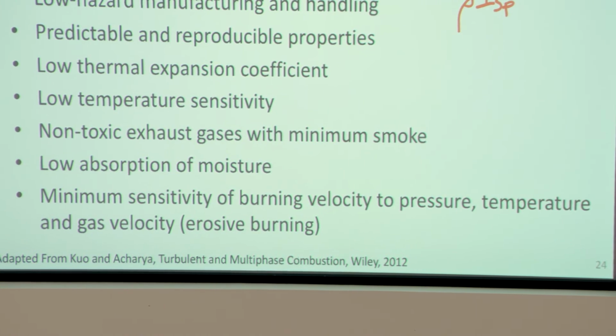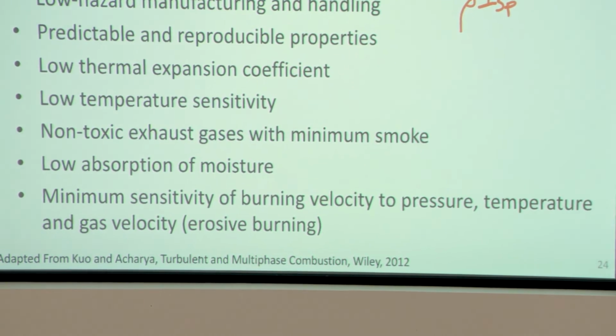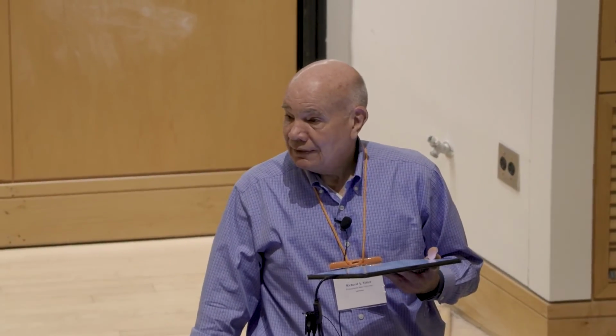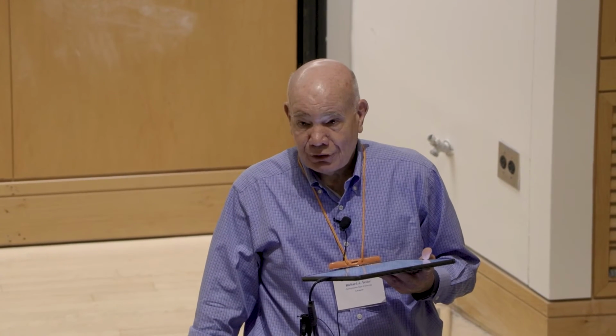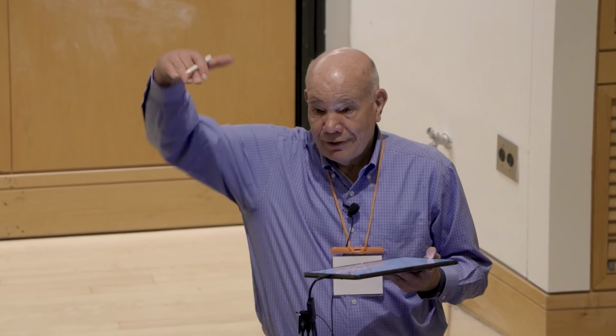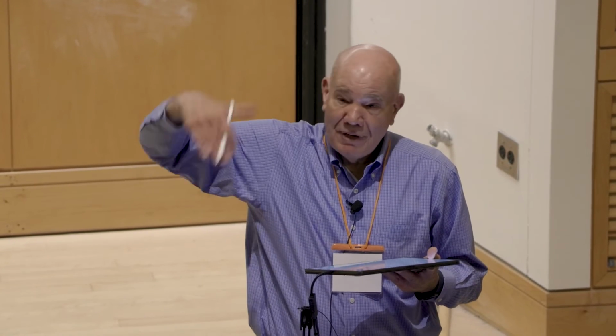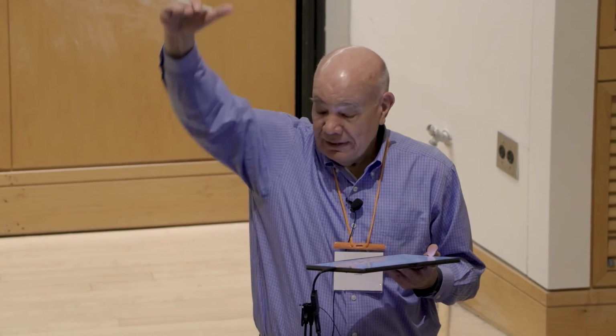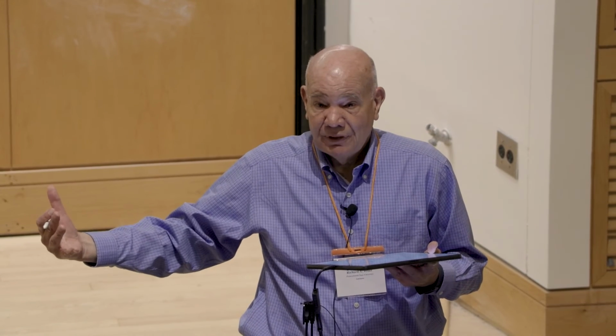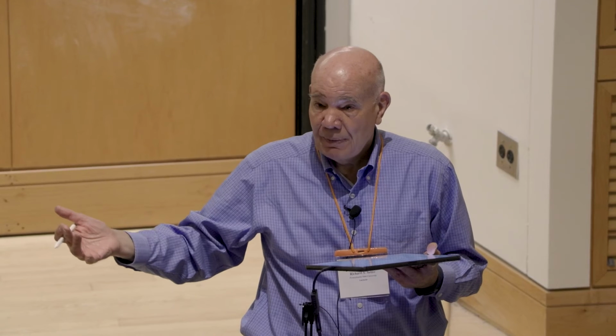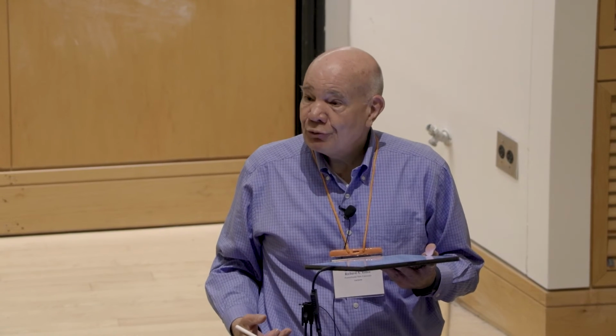What is the impact sensitivity, where I might have an energetic material here, and I drop a weight on it, and I look at whether it'll ignite or not, okay? And it's a very simple experiment where I keep changing the height of the weight, okay? And I measure then the height of that distance when it falls on the material and when it ignites, okay? So that's impact sensitivity. I can also have what's referred to as friction sensitivity, okay, where something rubs over the surface of the energetic material.